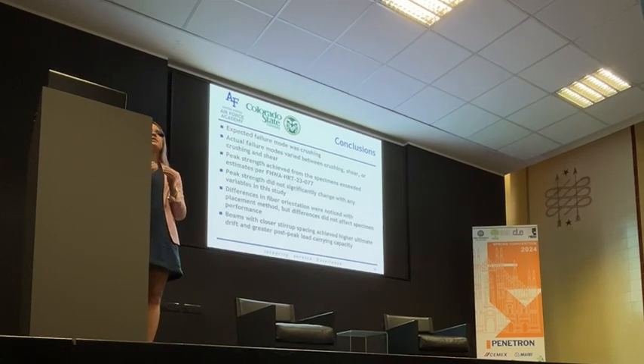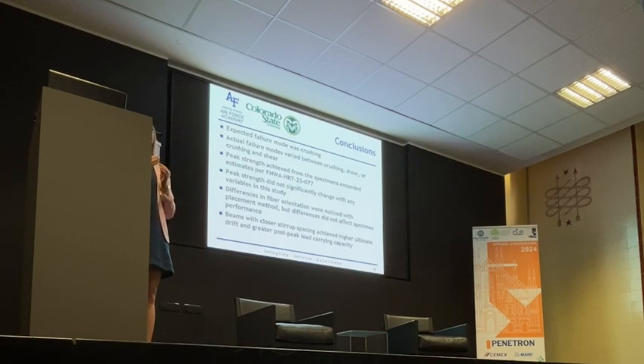But the peak strength didn't significantly change with any variables, and the differences in fiber orientation were noticed with placement method, but did not actually affect any kind of specimen performance. And beams with closer stirrup spacing achieved higher ultimate drift and greater post-peak load carrying capacity.